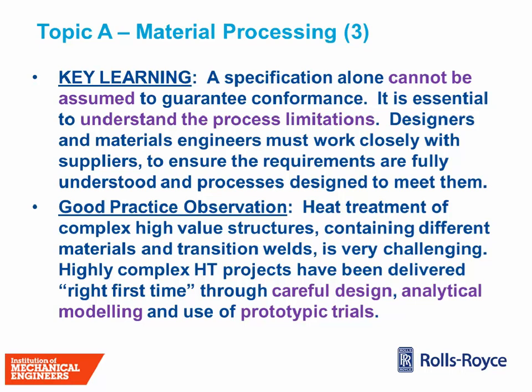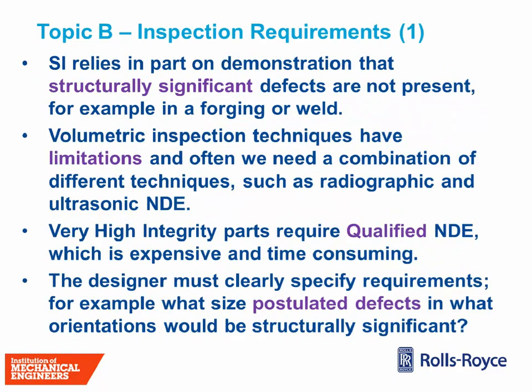We tend to put integrated project teams together. They work very closely. They design the heat treatment process very carefully. They use analytical modelling and FE analysis to predict what's going to happen to the component. And finally, I've seen pretty widespread use of prototypic trials, which are expensive and time-consuming, but result in a very high level of confidence that when you go and press the button on the heat treatment for your complex high-value structure, that heat treatment is going to be successful. So I thought it was worth sharing that good learning, because for big complex items we tend to put a lot of focus in. For less complex items we perhaps relax a little, and what I'm saying is you should follow the same principle for both, but apply the appropriate level of effort.